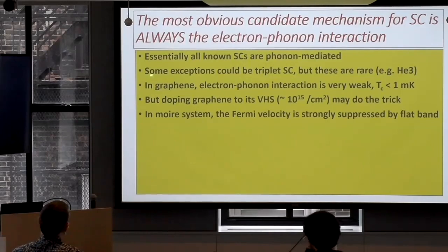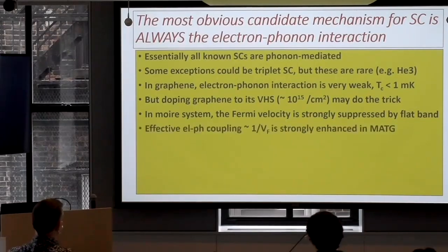So why is electron-phonon interaction in graphene important at all? Because in real graphene, just monolayer, TC is very low, as I told you. What happens in Moiré system, and this was really the only insight I've had, because Andrea Young called me and asked me why their resistivity is so large, 1,000 times larger than monolayer graphene, and it's linear. I said, oh, it's very simple. Fermi velocity is strongly suppressed. That increases the effective electron-phonon coupling, because that goes into the denominator of the effective coupling.